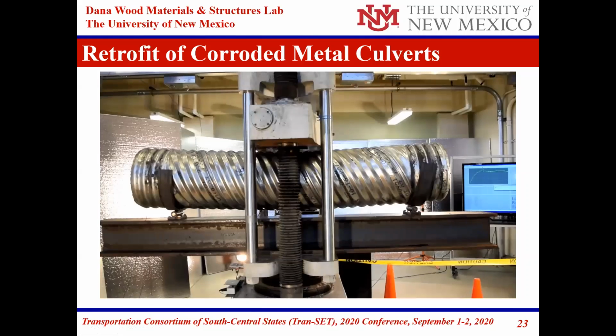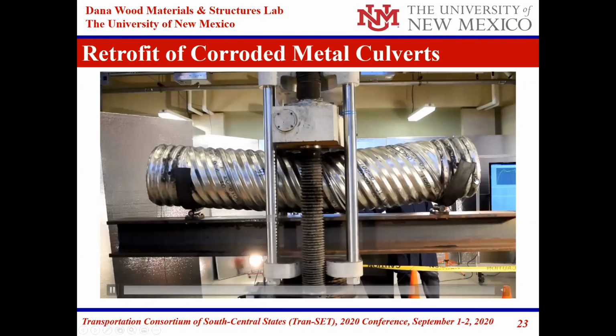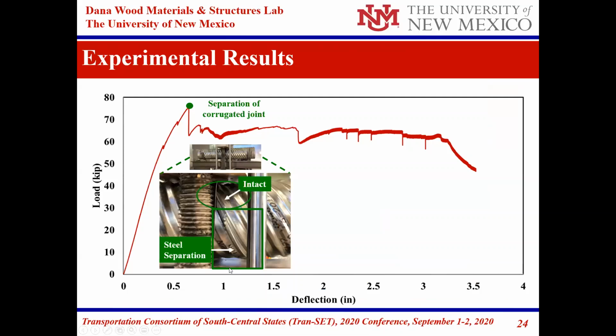So this is the load displacement, and you can see the load up to 76 kip, and you see the large deformation that is happening. So this is the test for the experimental results, 76 kip, and you can see very large deformation happening, which means that the new system is still ductile, wouldn't fail at once, because again of the bond between the GFRP and the pipe.